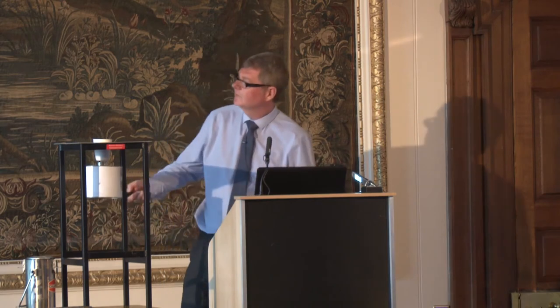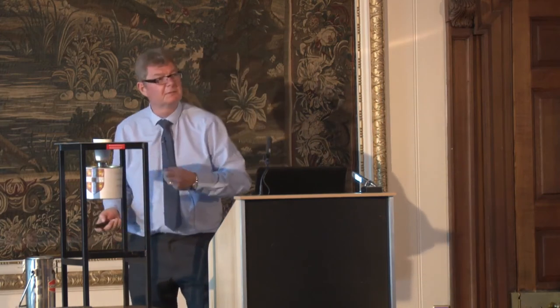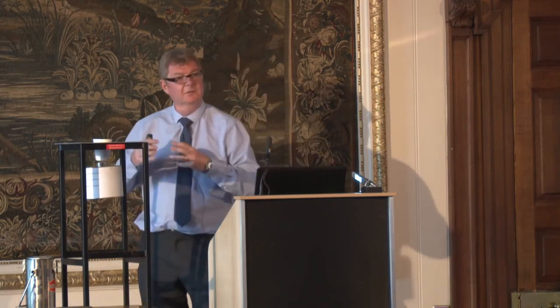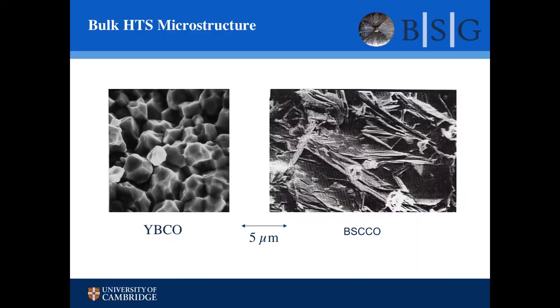There are one or two problems with these materials, though, and that is that although these temperatures are above that of the boiling point of liquid nitrogen, they tend to be ceramic materials. In sintered form, they have grain boundaries, and grain boundaries are not very good for carrying current, so you need to get rid of those grain boundaries. With lots of grain boundaries, you might get small current loops, but you need a big sample carrying a big current.